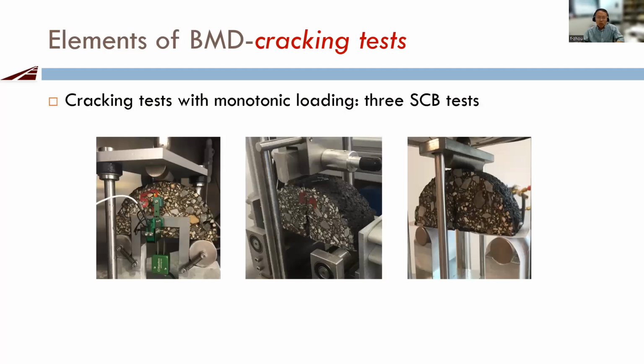So this shows you these 3 monotonic SCB tests. You look at the different loading frames, and although the specimen sizes are a little bit different, they're all semicircular, with a specimen chopped from the middle to get 2 semicircular specimens. All the specimens need a notch in the middle.